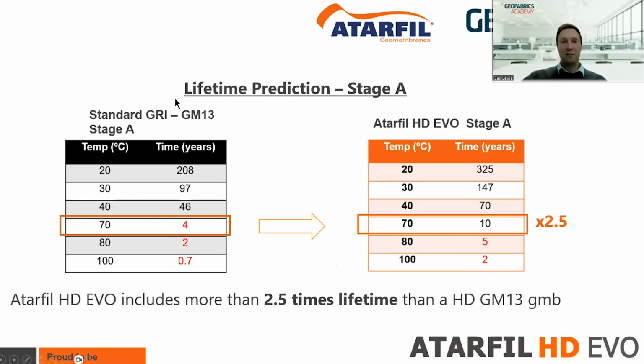And in terms of lifetime of these materials, or HDPE specifically, compared to what is available on the market, we are aligned with Atarfil, so I've shared some Atarfil information here. But if you were to look at the standard GRI GM13 specs in a temperature of, say, 70 degrees Celsius, now there's limited information I'm sharing here, but this is just for comparison's sake, you'd expect maybe only a 4-year lifetime. And you compare that to a superior product, which has got better stress crack resistance and other performance properties, you might get 2.5 times the life out of it. So it's certainly worth considering, even in low risk applications, if you want to get a longer performance out of it for not a huge cost differentiation.